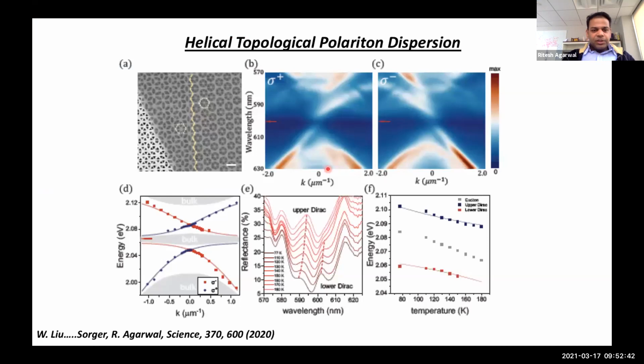So here's the experiment. What you see here is the underlying photonic crystal. On top of it, there's WS2. This is one type of lattice, and this is the other type of lattice. These yellow zigzag lines show the interface mode. With momentum space spectroscopy, one can map out these modes. These are the two Dirac cones. There are a lot of bands here, and there's a bulk gap here. These bands themselves have very interesting properties, which we are trying to explore now.